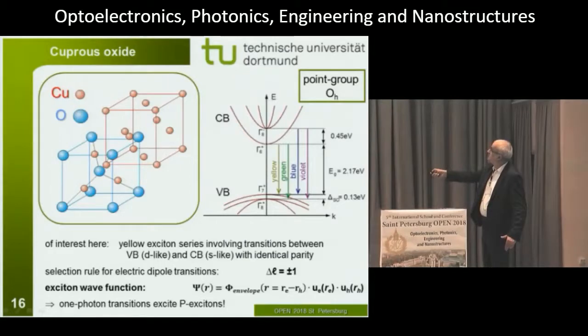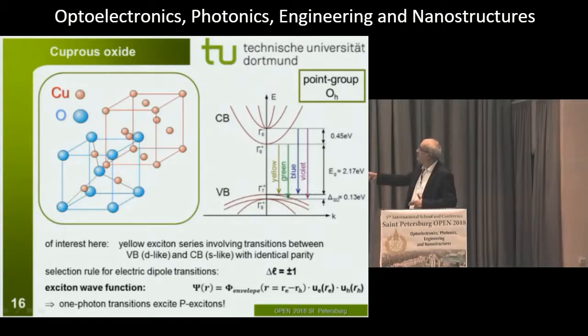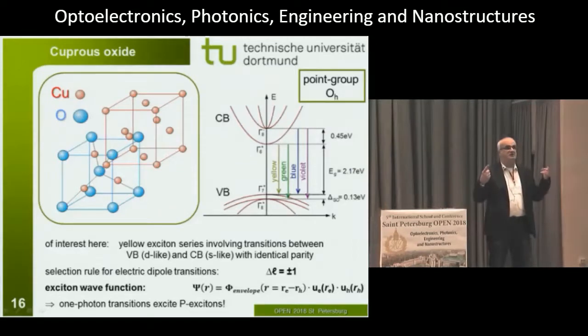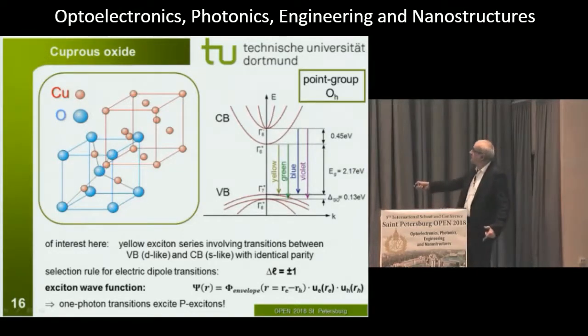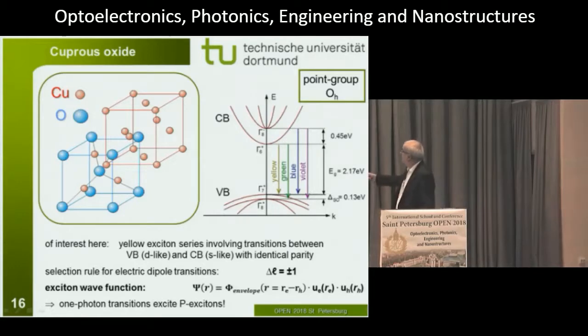The conduction band is mostly formed by S-like or S-type atomic orbitals, the valence band by D-like atomic orbitals. And there is obviously an angular momentum difference of 2. This tells you already that electric dipole transitions, for which the selection rule is written down here, are not possible. But if you involve the envelope wave function, you can make these states at least weakly allowed. Obviously, you come down from the angular momentum difference of 2 down to 1 by involving an envelope wave function of p-type. So what we can excite, and this is also what Gross excited, were p-type excitons.